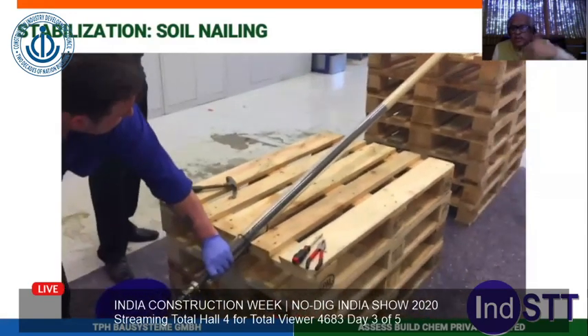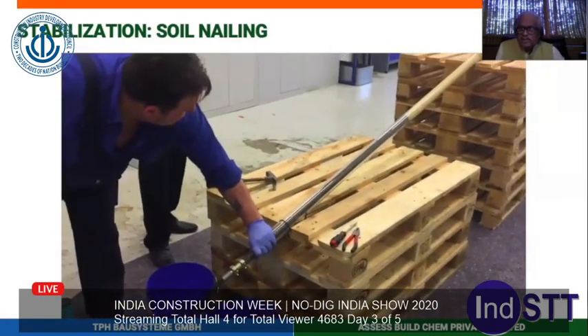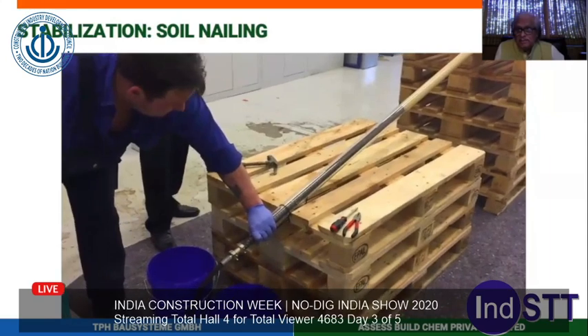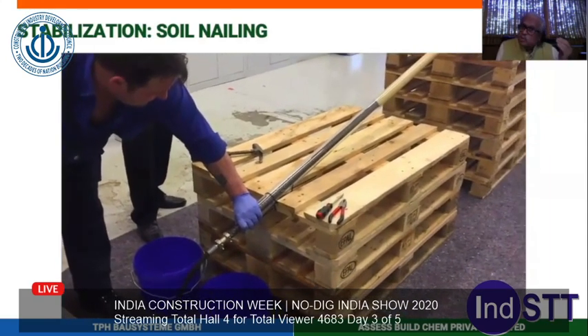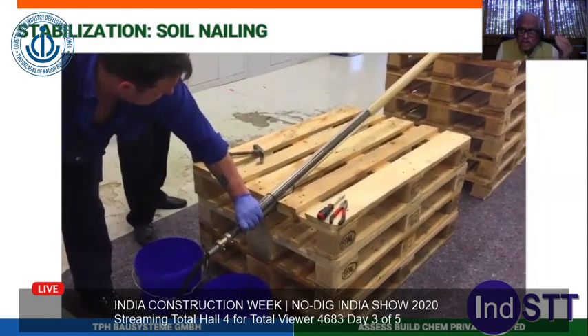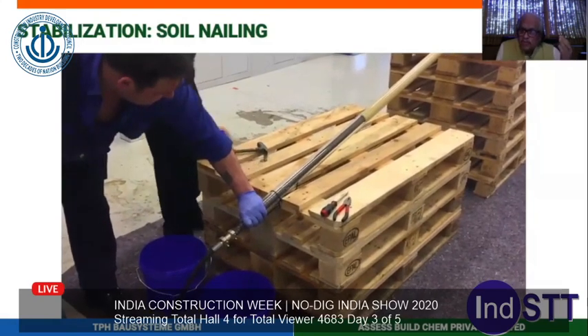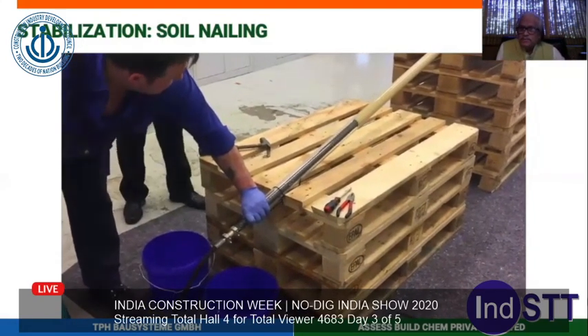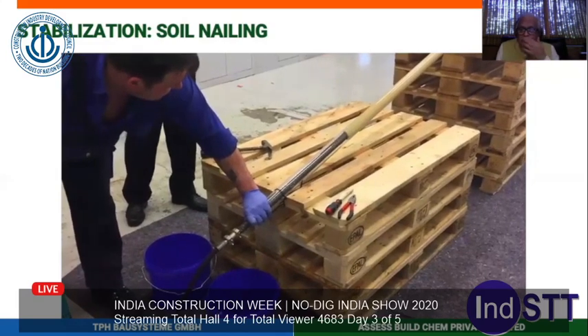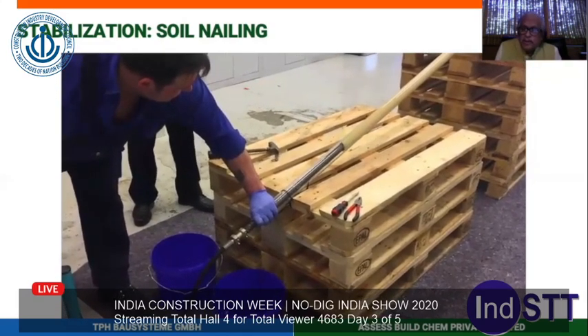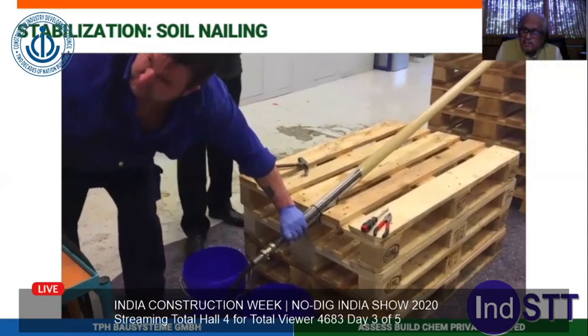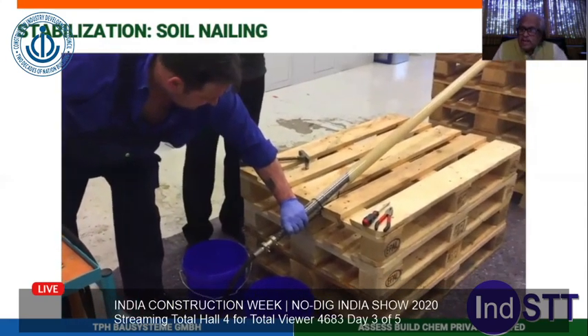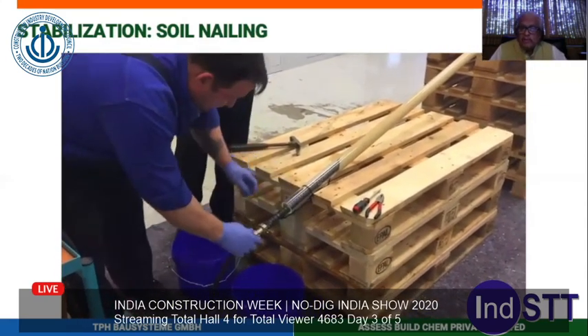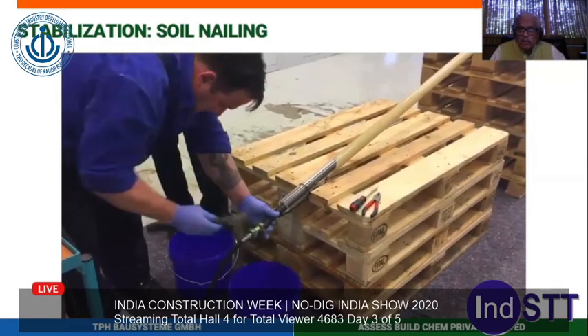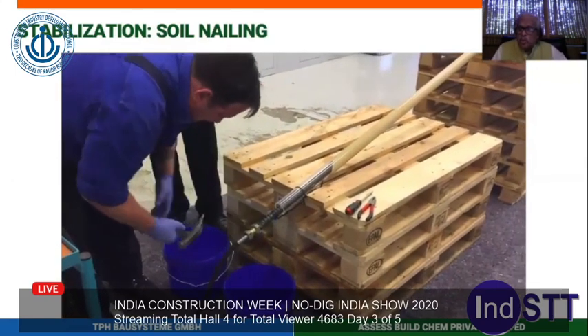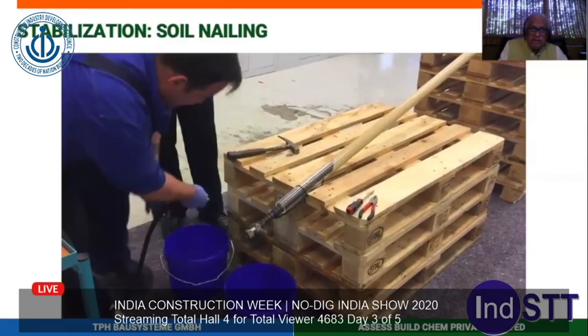He said repairs are to be done by 2-component polyurethanes. This does not say anything. The performance criteria should be given. What strength you require for repairs, what viscosity is required, in how much time. For example, this develops a pull-out load up to 20 tons within about 10 minutes. Within about 10 minutes, your reaction is over. It is developing the full strength.